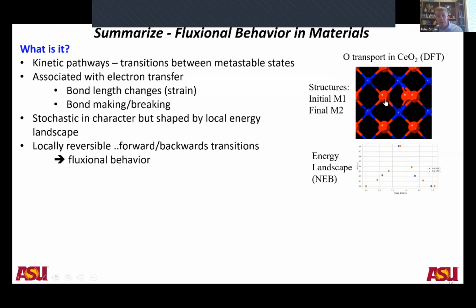And here's just another example from Tara Boland. She's looking at transport of oxygen, again, this is oxygen transport in ceria. And here's the structure as she does this NEB calculation with DFT. And here's the energy landscape. She calculates an activation energy barrier of about 0.8 eV, which is about the right value and matches experiments. And so you could say that when the oxygen is on the left-hand side, that would correspond to structure M1, and when the oxygen is on the right-hand side, that would correspond to structure M2.